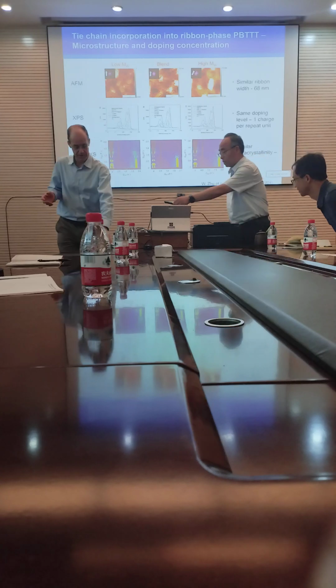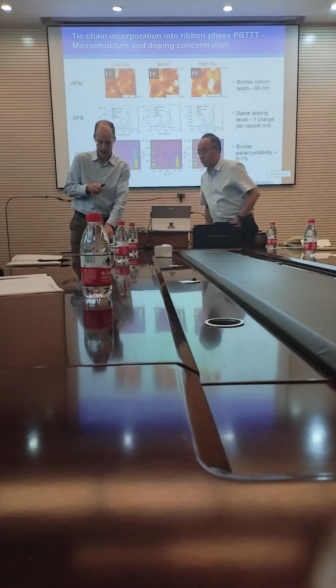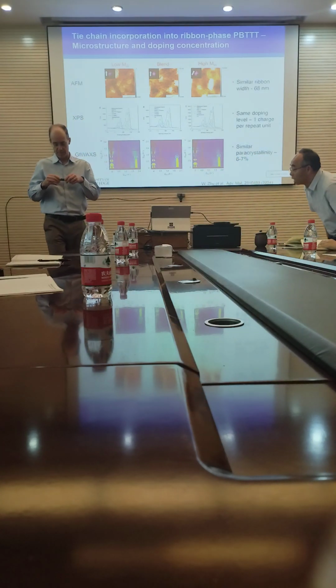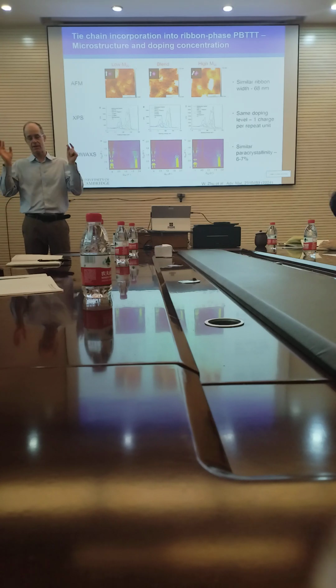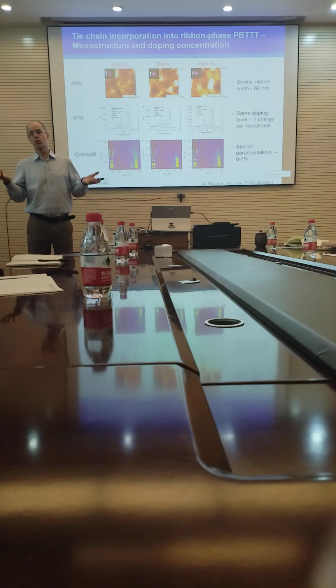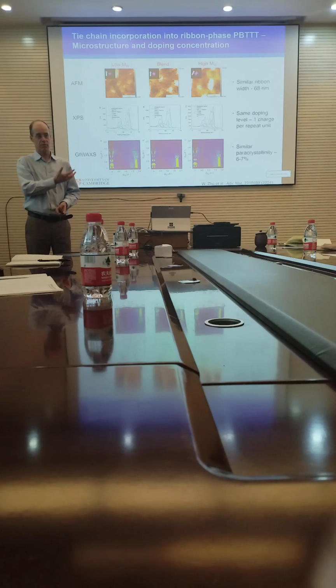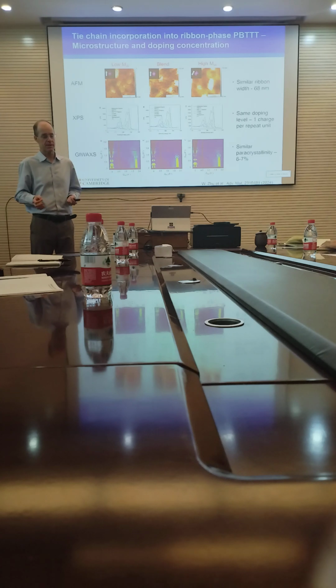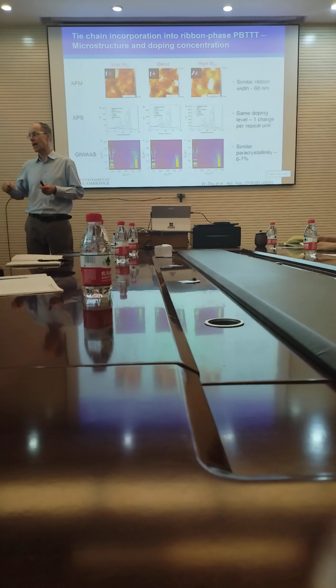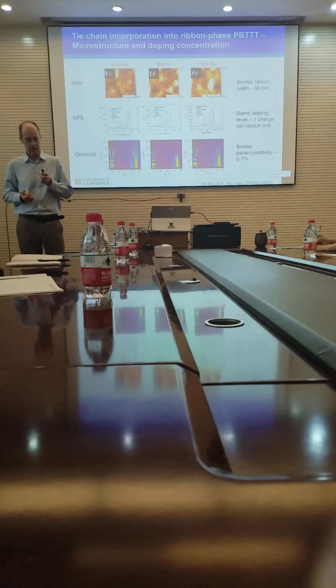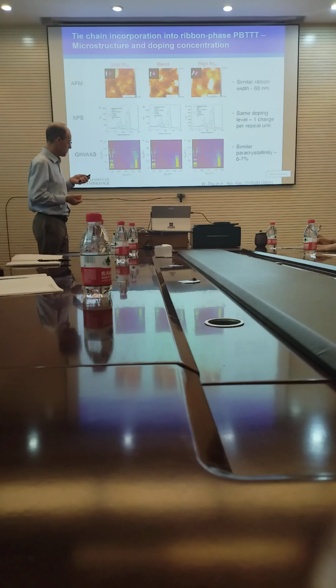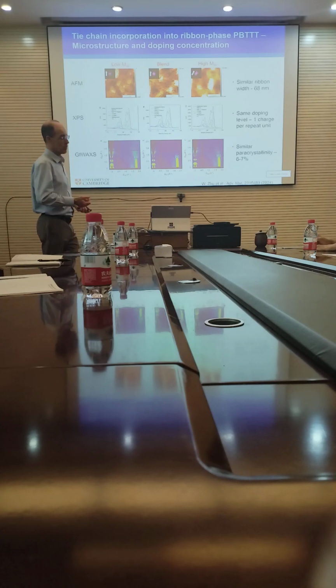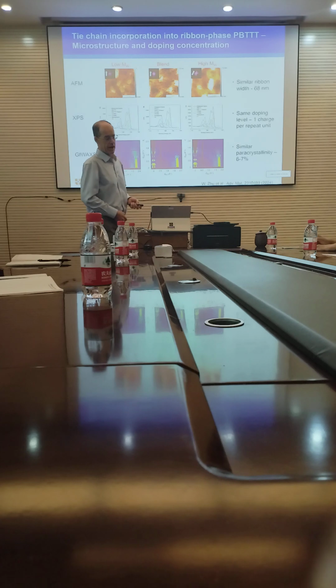So with none of these techniques, we were able to see a difference. So the polymers have the same charge density, the same microstructure. So we concluded that the only reasonable explanation for this improvement is indeed the hypothesis that we have these tie chains and they do increase the conductivity in the way I explained. So we now have a model system where we can study the thermoelectric physics.